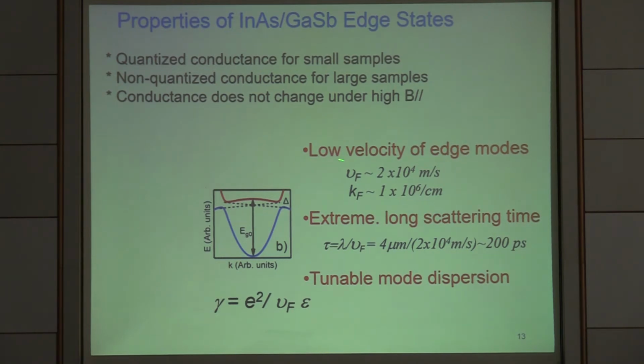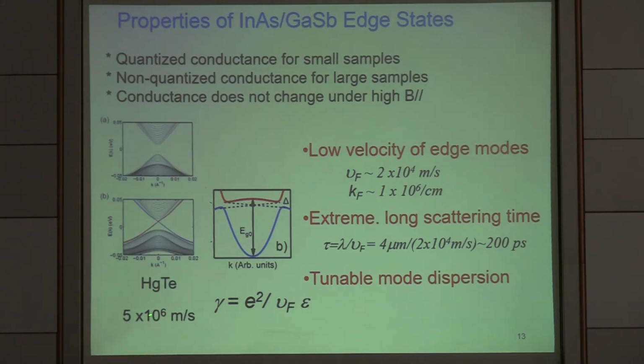First we notice the velocity of the edge modes is extremely small. Here one can estimate the velocity to be on the order of 10 to the 4 meters per second. And of course, if we compare this to semiconductors, it should be 10 to the 6 meters per second. Mercury telluride is also about 5 times 10 to the 6 meters per second. So our system is in a region particularly with low velocity of edge modes. Now, if the edge modes have a very low velocity, it means the kinetic energy is relatively low compared to the interaction energy. Therefore, we can characterize this as a strongly interacting one-dimensional edge state rather than a non-interacting edge state in this particular type of device.